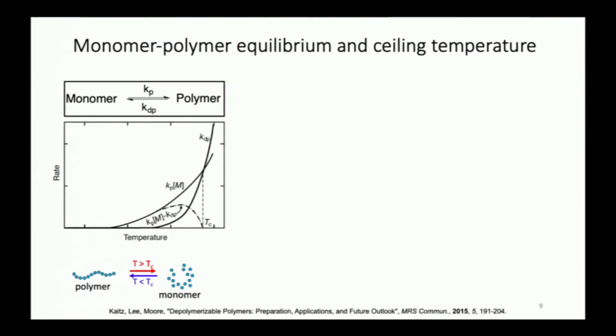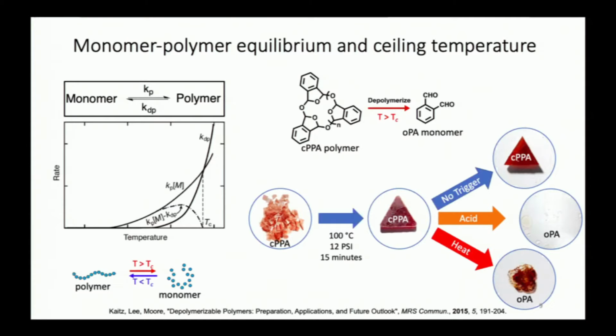And so we wonder, can we simply reduce the problem down to finding low ceiling temperature polymers? Certainly my group, Adam Feinberg in my group, Evan Lloyd, as well as Hector Lopez, have looked pretty carefully at this particular polymer. It's been in the literature for several decades. The cyclic polyphthalaldehyde, you'll notice it has no end groups, which is key, because as soon as you create an end group, this particular polymer is quite sensitive to depolymerization, because at room temperature we are well above the Tc, the ceiling temperature, and it prefers to go back into monomer. But you can kinetically stabilize it in this form, provided that you keep it away from things like acid or heat, at which point it will revert back to monomer.